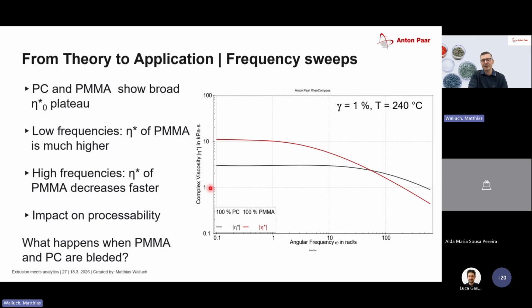So in the low frequency area, we see that the viscosity of PMMA is much, much higher, and the viscosity of PC is much, much lower. But if we increase the frequency, or the shear rate would be the same, we see that the material, the PMMA, gets to flow much, much earlier. And at a certain point, we have this crossover. So here the material, the PMMA, has a lower viscosity than the PC. This is important if we want to have a look at the process itself, and if we want to combine this material, so we can blend PC and PMMA. What happens then?